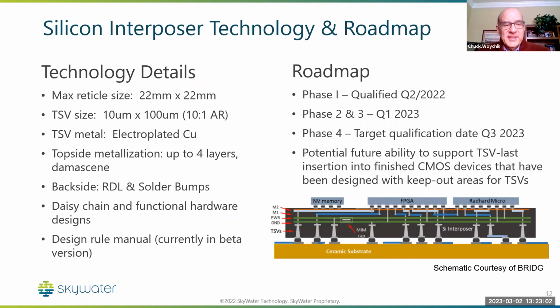If you really look at the technology details, they're outlined on the left-hand column. But the important thing right now is our chemistry is electroplated copper, and we have the four metal layers of copper damascene that we can build up. For the phase 3, it's a little more sophisticated, more layers. In the future, we want to have organic RDL structure, and I'll get into that discussion as we get into the DECA technology. Typically, as you well know, the backside RDL structure is a polyimide buildup type of structure, and that's what we plan to use on the backside for our RDLs, and it will also be solder bumped.